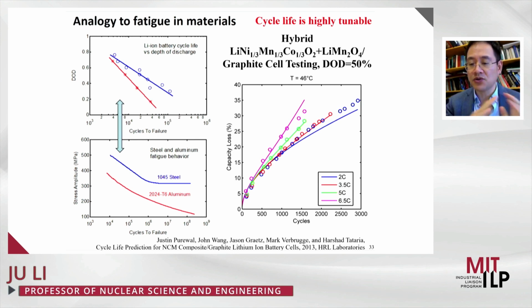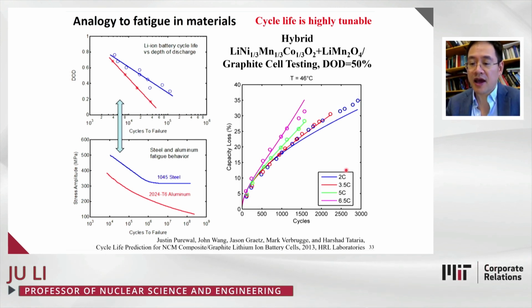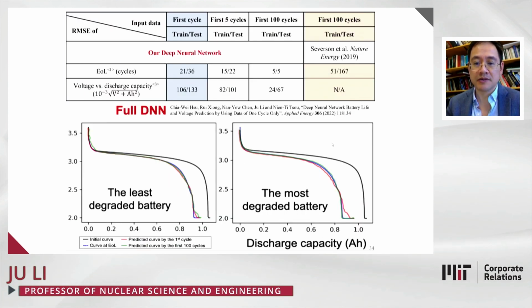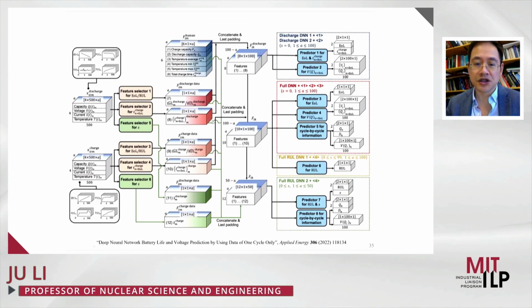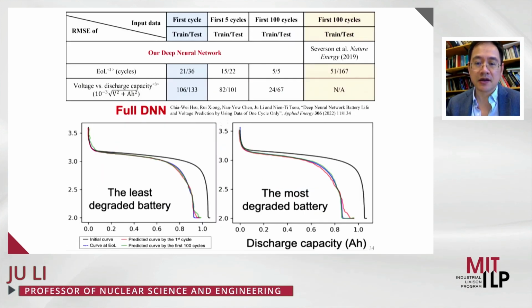On one hand, you want to do fast charging, but on the other hand, do you really need fast charging in this particular case? So knowing what the customer wants and to do the best trade-off is quite important. And in this work, we have developed a deep neural network, which takes in just one cycle of additional battery tests, and we're able to predict the residual life of the battery to within 20 cycles.